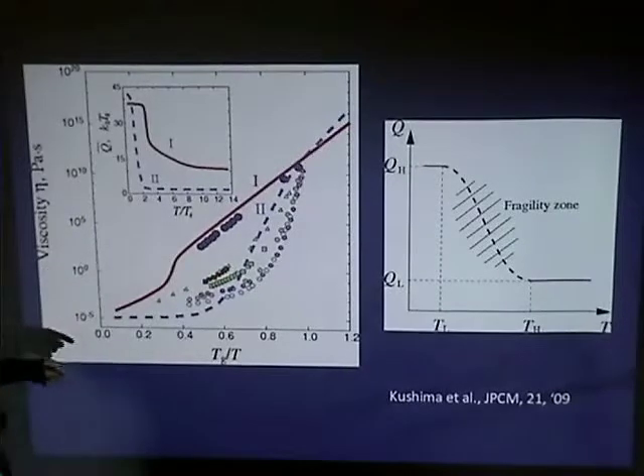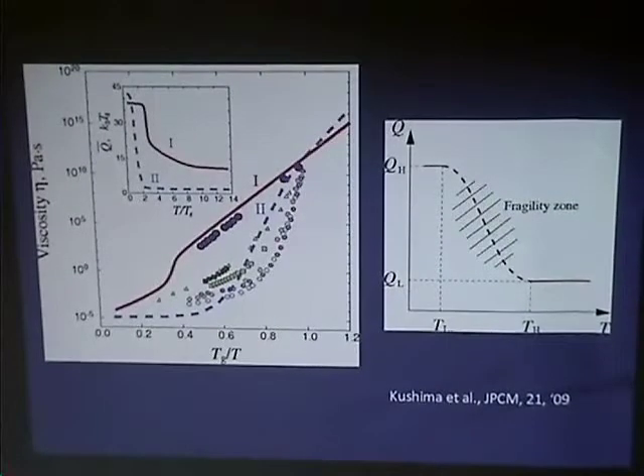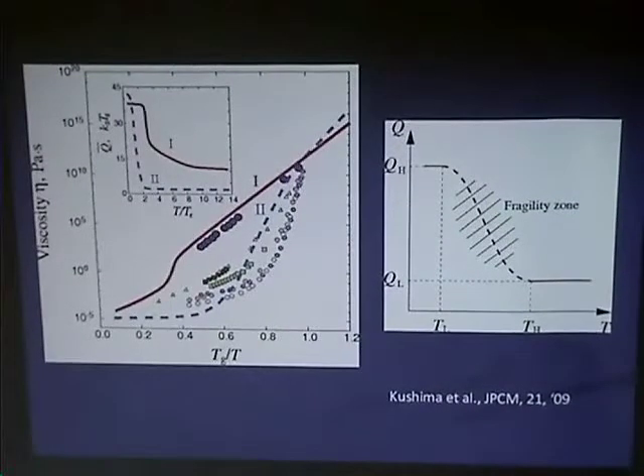So this is the well-known plot, and everybody looks at this plot and thinks in terms of viscosity. If I were now to write a very simple transition state theory expression for viscosity, eta, let's say it goes like eta naught, e to the activation energy, call it Q bar, some sort of averaged coarse-grained activation energy over kT. There are plenty of people who use this kind of expression. In fact, it goes back to Andrade back in 1932. There was a little note in Nature that actually said that.